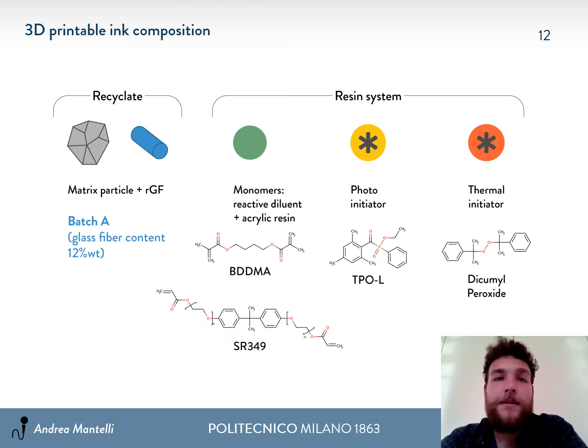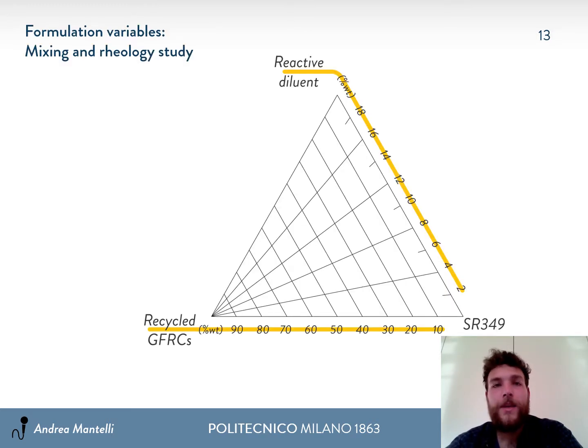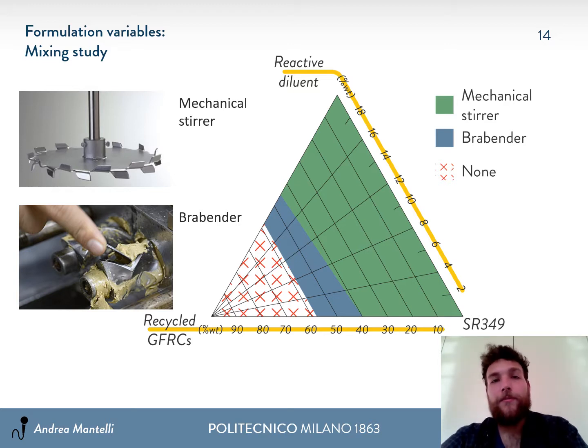First of all, the premise. Here you can see the main components of our blend: a photoactive resin, a reactive diluent, a photoinitiator, and a thermal initiator. These components create a resin system to which we can add the recycled material in the form of fine powder. In order to find the best conditions for mixing the material, we defined a grid of formulations to make the tests. And experimentally, we have been able to define which formulation can be mixed with a mechanical stirrer, which can be mixed with a thick paste mixer like a blender, and which cannot be mixed to produce a homogeneous material.